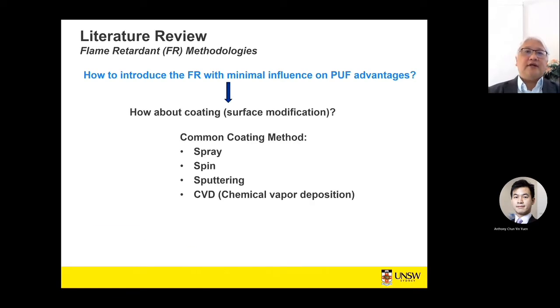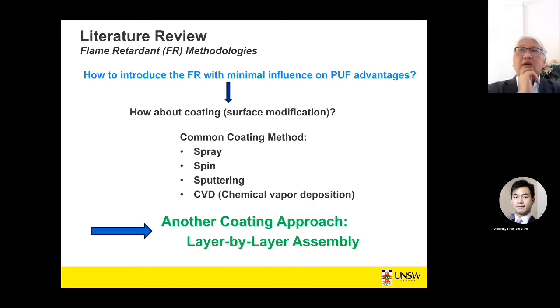So the question here is, could we introduce flame retardant with minimal influence on the polyurethane? The answer is, yes, we can. For example, we could take the original foam itself and apply a coating. The coating can be realized either by spray, spin, sputtering, or chemical vapor deposition.